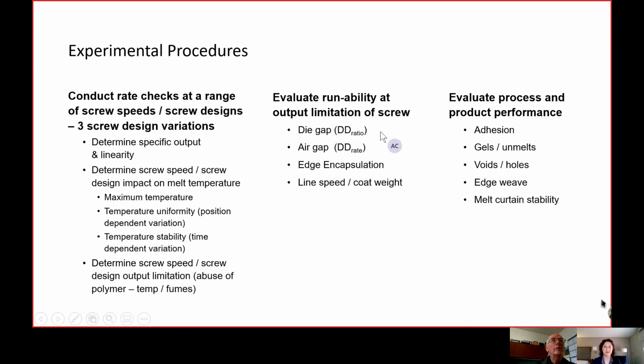The other things that we looked at were the drawdown ratio, which we were able to reduce by reducing the die gap, and the rate of extension, which is impacted by the air gap, so the distance between the die lips and the coating nip. We did one brief look at edge encapsulation, and that's introducing a secondary polymer only on the edge of the melt curtain to then allow for higher line speeds by stabilizing that edge. So this was all done for the ability to try and increase the line speed while reducing coat weight to create a PLA-coated product at reasonable production speed.